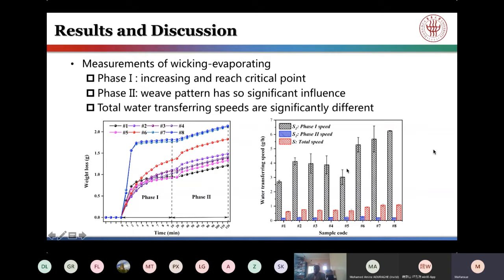Additionally, in this figure, we can see that these characters could be divided into 2 groups. Group one includes sample 1, 2, 3, 4, 5. And their floats are distributed evenly throughout the entire fabric surface. While group 2 includes vertical striped fabrics from sample 6 to sample 8. And their total water transfer speeds are higher than that of group 1. So you can see the difference between the two groups.